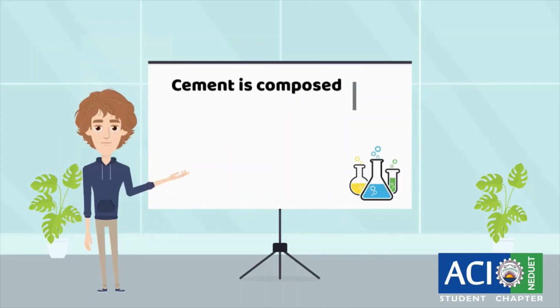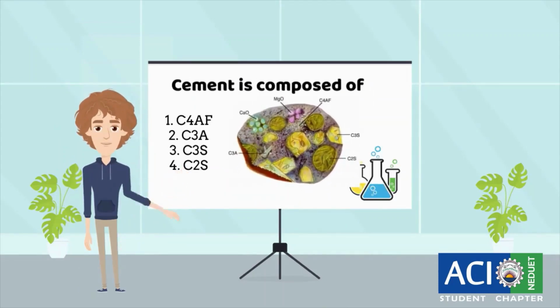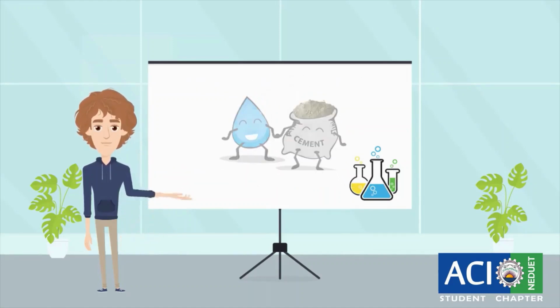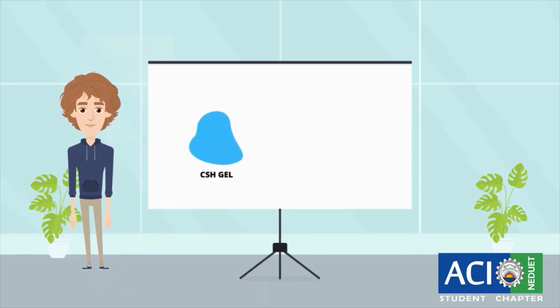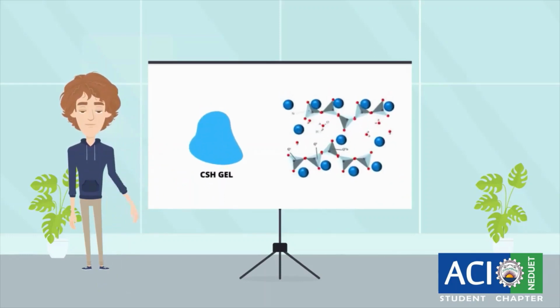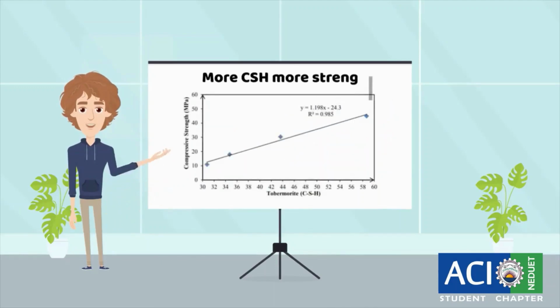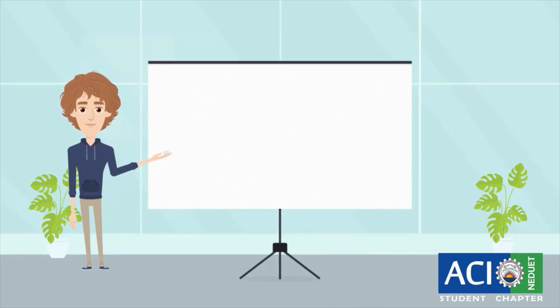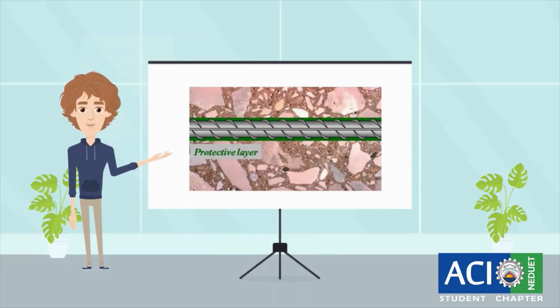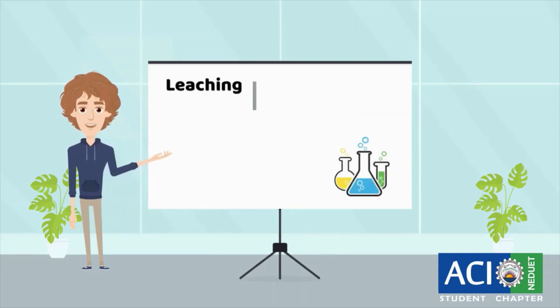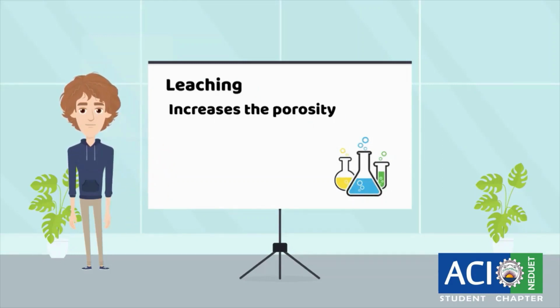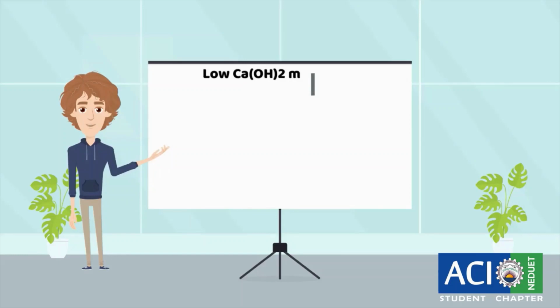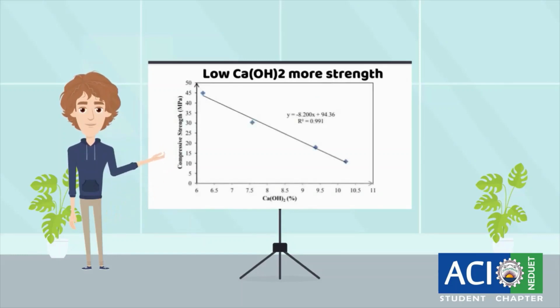Cement is composed of 4 main compounds, namely tetracalcium aluminoferrite, tricalcium aluminate, tricalcium silicate, and dicalcium silicate. When water is added to the cement mixture, hydration products such as tobermorite gel, also known as CSH gel, and calcium hydroxide start depositing on the hydrated cement. CSH gel largely contributes to the strength of concrete. The other compound, calcium hydroxide, is able to protect reinforcing steel from corrosion. However, calcium hydroxide also causes leaching. Leaching of calcium ions increases the porosity of cement-based materials, providing an entry for aggressive harmful ions, which cause the steel reinforcement to corrode in later times, resulting in a negative impact. Thus, when calcium hydroxide is lowered, compressive strength is increased.